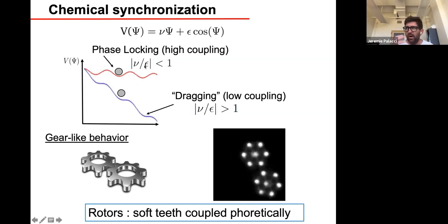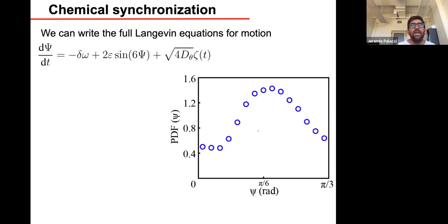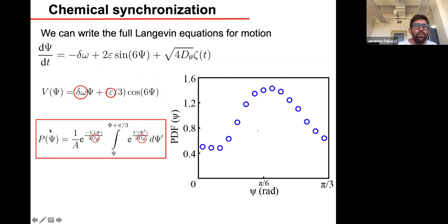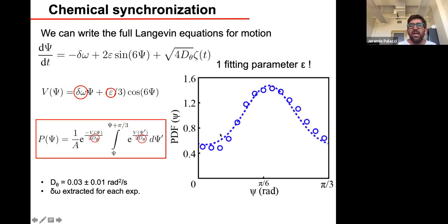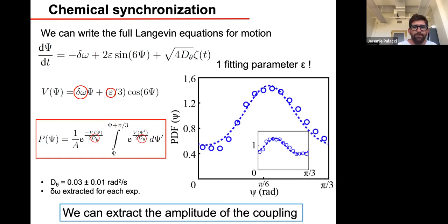So that was kind of the hand-wavy argument to explain what was happening and how it accounts for the gear-like behavior we observe. But we can actually write down the full Langevin equation for the motion and predict the probability distribution for the phase lag. So the dots here are the experiment, and the dashed line is our prediction with only one fitting parameter. So it captures our experiments very well, knowing that all the other parameters, like the amplitude of the active noise or the speed of the rotation, are measured independently. So we really have only one fitting parameter.